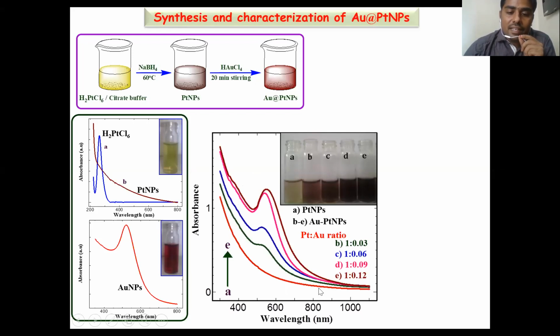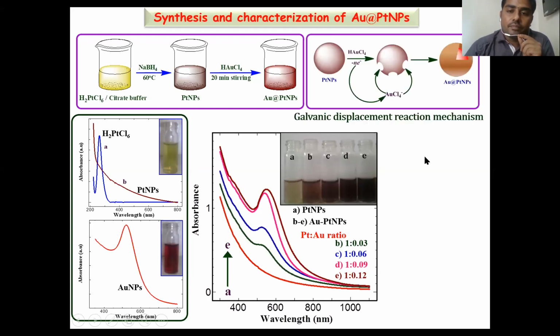Initially the platinum nanoparticles do not show any SPR. After adding the gold auric acid to the solution, the color changed from brownish yellow to brown, and we observed an SPR at 530 nanometer. When we change the mole ratio of gold auric acid to the platinum nanoparticles, with the formation of gold platinum nanoparticles, the SPR gradually increases, and at the 1:0.12 mole ratio, it attains saturation. So it follows the galvanic displacement reaction mechanism.